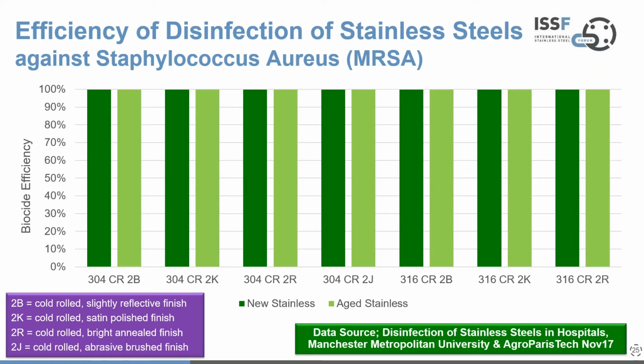And then we have 2 sort of categories of stainless: brand new stainless at the moment of installation, and aged stainless some years down the line, been in service for some time. And what's impressive is that the biocide efficiency is close to 100% for all these materials, and the aged performance is no different to the new performance. So this is a method of verifying that stainless steel throughout its operating life is still disinfectable to a very high degree of efficiency. So this is a really good test that demonstrates that the material is suitable for healthcare